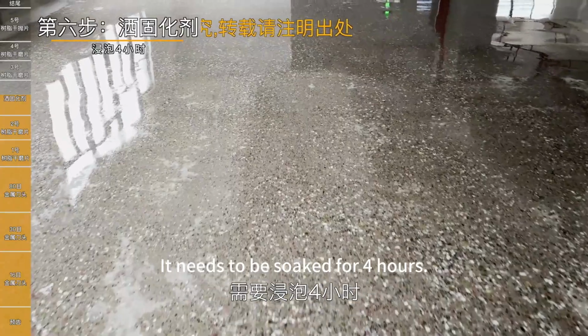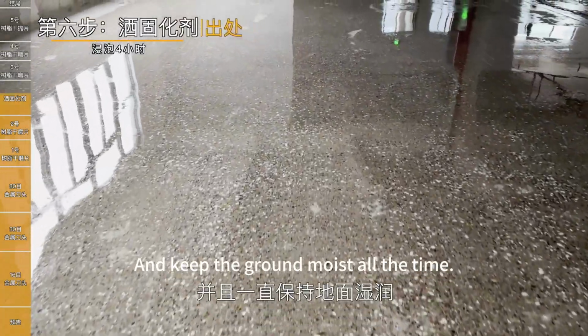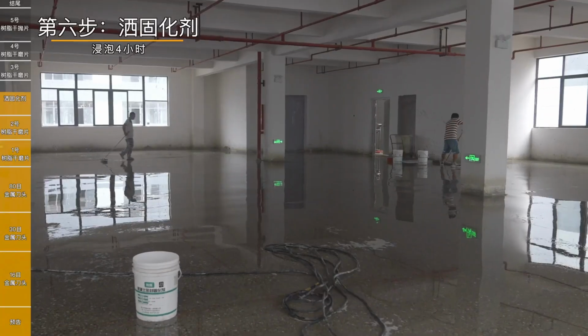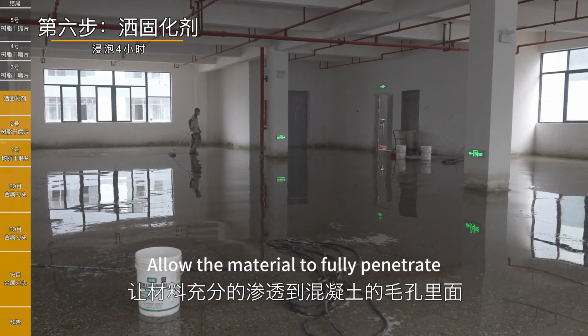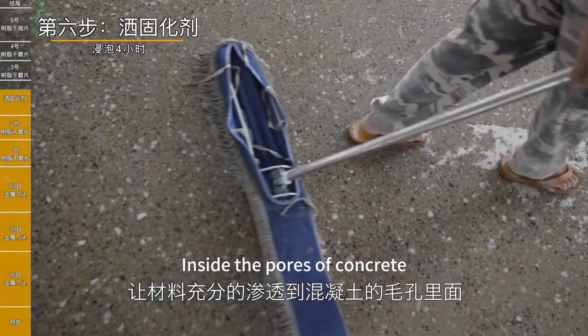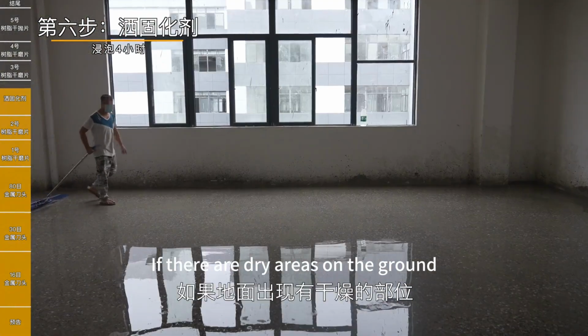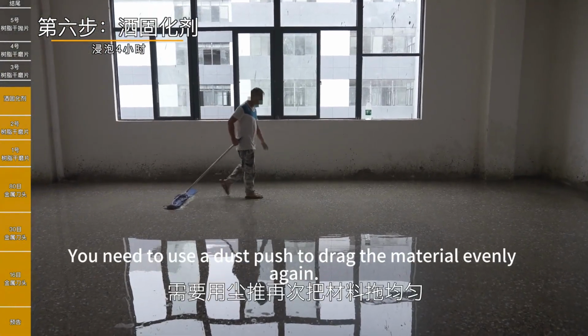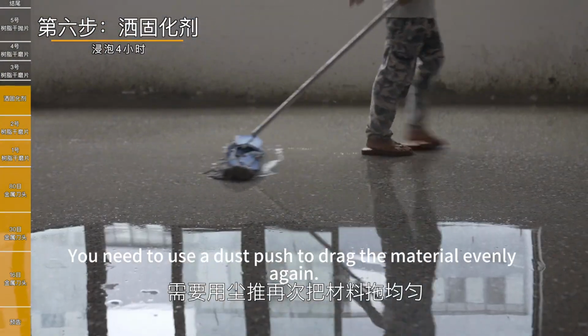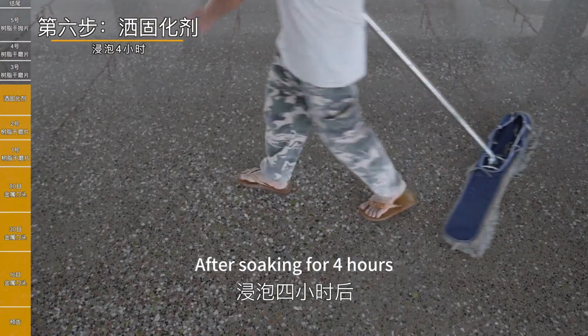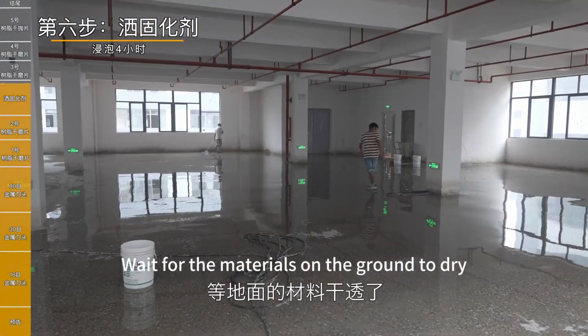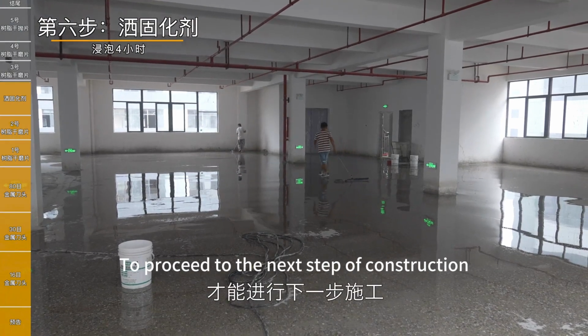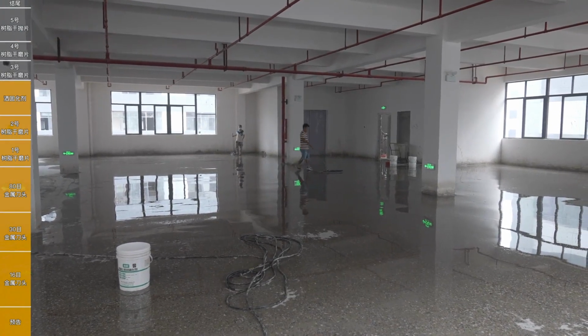It needs to be soaked for 4 hours, keeping the ground moist all the time, to allow the material to fully penetrate inside the pores of the concrete. If there are dry areas on the ground, you need to use a dust pusher to drag the material evenly again. After soaking for 4 hours, wait for the materials on the ground to dry to proceed to the next step of construction.